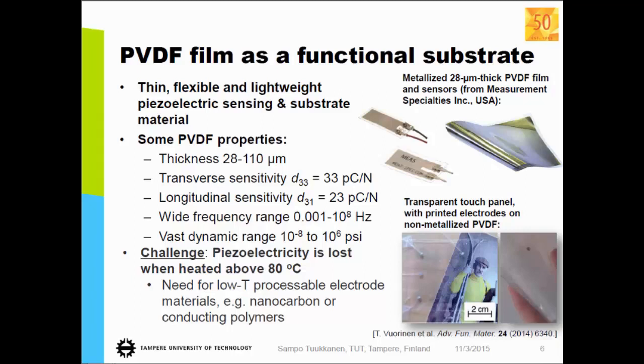And this is an example of what we did more than 1 year ago, that we used transparent conducting ink and then made the electrodes on both sides, and we can have nice flexible transparent touch panels basically. And the good thing about the piezoelectric panel is that it works in water. Capacitive sensors have some problems with humidity and water, so that's one interesting aspect.